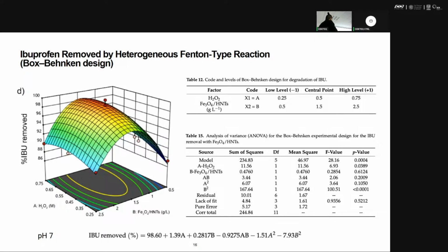So this is the result I measured with the Box-Behnken design. Once I found the optimal condition, I used those conditions to be sure with another measure. I use COD to find the mineralization, because this just gives you the oxidation of the ibuprofen, but doesn't tell you the quantity of mineralization. For that reason, COD was used, and it found that the ibuprofen was mineralized about 60%. And even more, with this condition, I also use an HPLC analysis to find exactly the amount of ibuprofen which is degraded, and if it is mineralized or not.